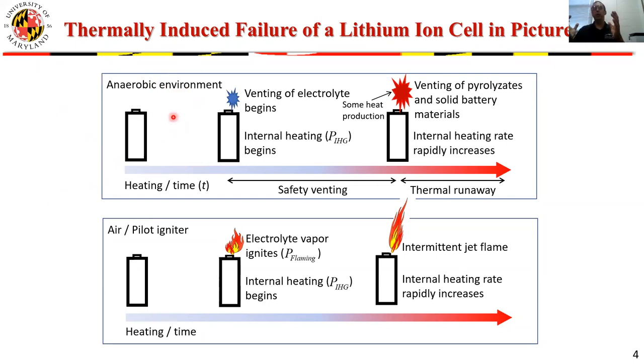So you have an anaerobic environment. You heat up this cell. And as you heat up this cell, you raise the pressure inside the cell because electrolyte evaporates. Your safety vents will open at a certain point. And somewhere right after the safety vents open, you start triggering this thermal runaway inside the cell. So the heat starts being produced inside the cell itself due to these chemical reactions that I mentioned a couple of slides ago.